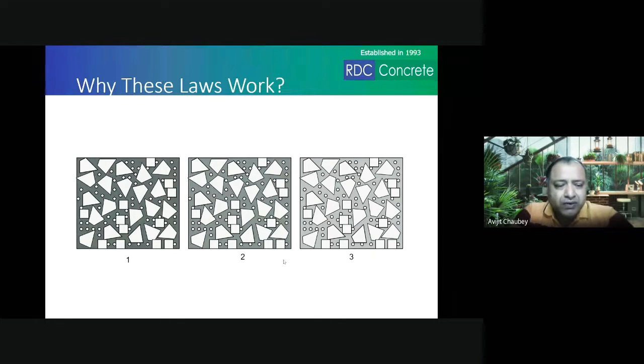When you do the reverse working, that would be 2000 kgs of cement per cubic meter, more than 2000. And that is what he got when making a concrete or a cement paste at a very low water cement ratio. So don't expect that you will get a strength higher than 100 MPa with the same materials that you are using.